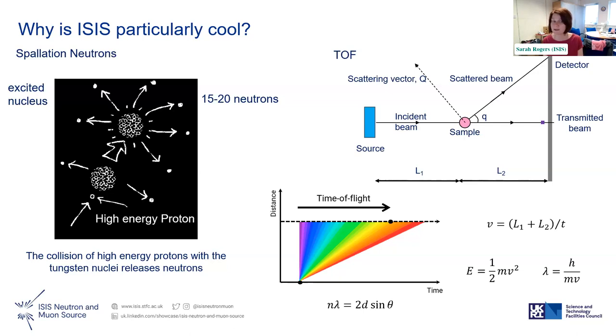And for every proton that goes in, we get about 15 to 20 neutrons. That smashing process at ISIS happens 50 times a second. So it is quite a number of neutrons that we produce. And obviously those neutrons come off at all sorts of crazy energies. We slow them down with things called moderators that slow the neutrons down to an energy or wavelength range that's actually usable. We have different moderators on different parts of the target system, depending on the speed or the wavelength that you're interested in. So for example, excitations want warmer neutrons than the large scale structures people. SANS and reflectivity really like the cold neutrons. So we have a range of moderators that slow them down.